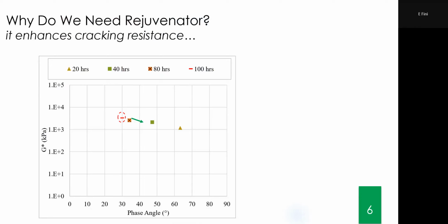So here in the DSR, for those of you not familiar with DSR, it is just a measure of shear resistance. So the higher the resistance of material to shear deformation, you get a higher modulus, complex modulus. It's done on an oscillation type test, and we name the test as dynamic shear rheometer. So regardless of the method here, we are measuring the shear resistance. And as you can see here, the shear resistance of the material at different hours of aging, 20 hours, all the way to 100 hours, is different.